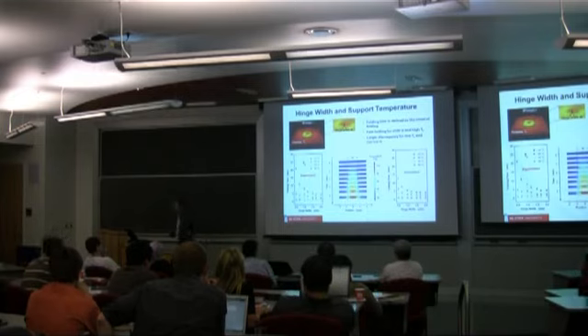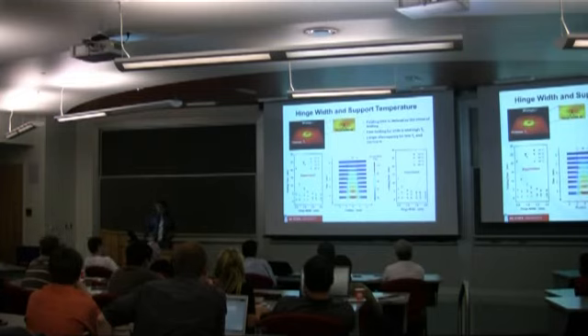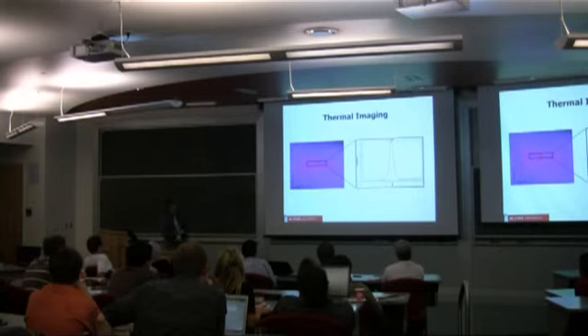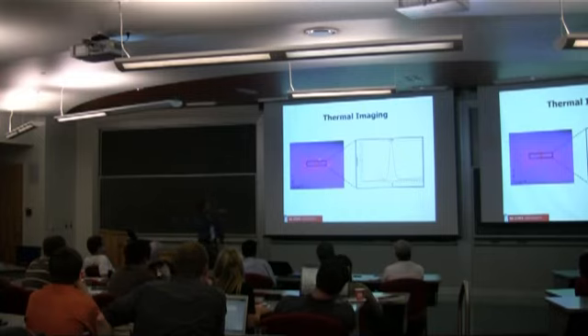Now here's where it was exciting for us. We went into the lab and used an IR camera and measured the temperature of the hinge when it starts to fold. So this is an IR camera image of the shrinking ink. And you see that it's sort of uniform everywhere except at the hinge. It's glowing red, which means it's hotter.